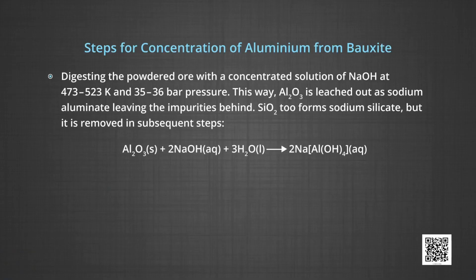The first step, digesting the powdered ore with a concentrated solution of sodium hydroxide at 473 to 523 kelvins and 35 to 36 bar pressure. This way, alumina is leached out as sodium aluminate, leaving the impurities behind. Silica too forms sodium silicate, but it is removed in subsequent steps.